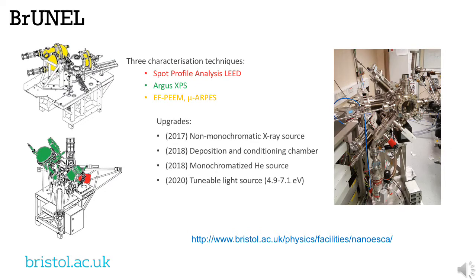The Bristol Nanoesca has been in full operation for just over 2.5 years, and during this period has had 3 equipment upgrades to the instrument platform to support user requirements, including an additional X-ray source, an ultra-high vacuum preparation chamber for sample annealing, sputtering and E-beam deposition. The latest upgrade to the Nanoesca is the laser-driven light source to allow users to probe surfaces with light in the 4.9 eV to 7.1 eV range.